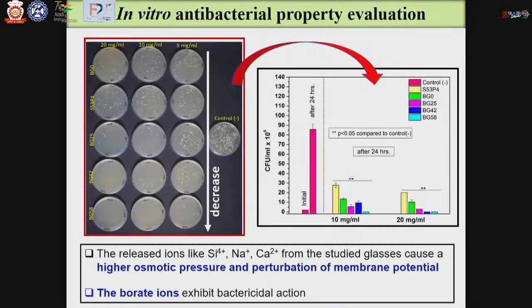We have also assessed the antibacterial property. With borate ions, with the increase in B2O3 content, the glasses show increasingly higher antibacterial property, and these glasses have quite good antibacterial property against E. coli bacteria, which is a gram-negative bacteria and quite often involved with osteomyelitis disease.